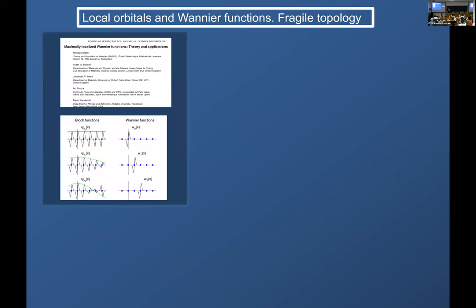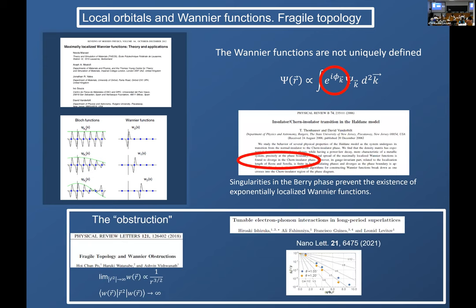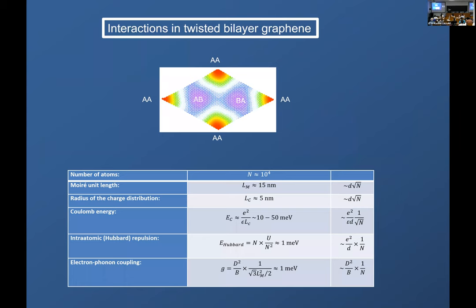There is a question of how useful these Wannier functions are—the question of the obstruction. You have, as I said, if you define wave functions starting from individual valleys, you have to pay the price of power law tails. They are not exponentially localized. Moreover, Wannier functions—I have to warn you—are not uniquely determined. You have to optimize them, but you're never sure that you are choosing the best Wannier function appropriate for the problem at hand. But nevertheless, they have a well-defined form and they are normalizable. The power law tail doesn't imply that they are not normalizable, so they are actually not that useless as some people may believe. You can take them and calculate umklapp processes and things like that related to the model.